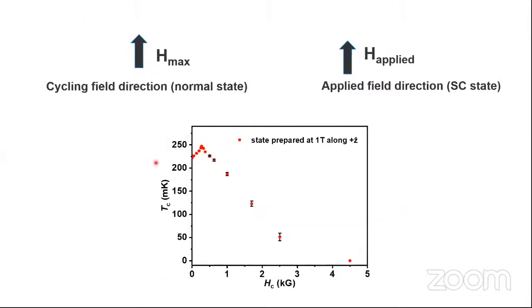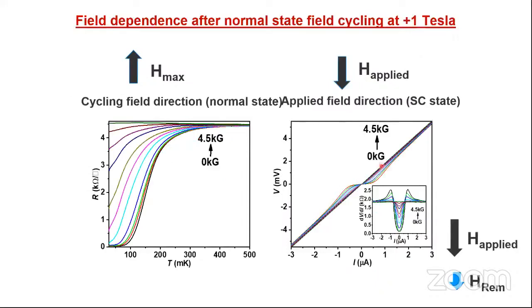This is the HC-TC phase diagram for the magnetic field applied in the same direction as the cycling field, and H max is the maximum field to which cycling was done. In this case, it is 1 Tesla. And we see that the critical temperature goes up, then it goes down systematically. Now what we did, we applied the magnetic field in the other direction. So the maximum cycling field was in the upward direction, but the measurement is being done by applying a field in the downward direction.